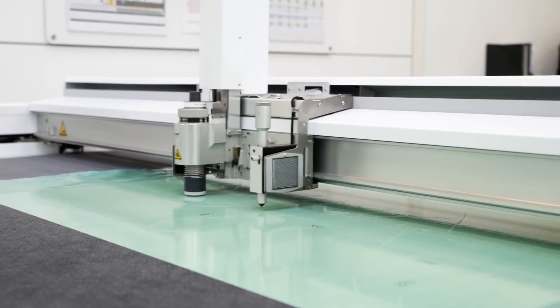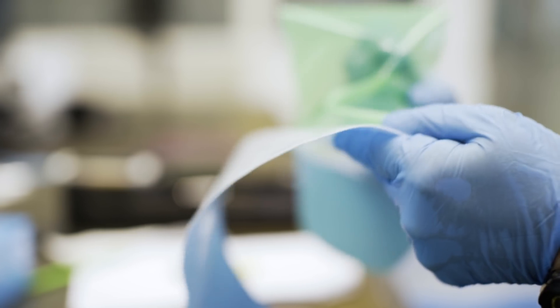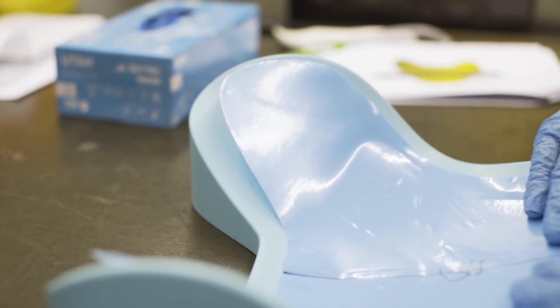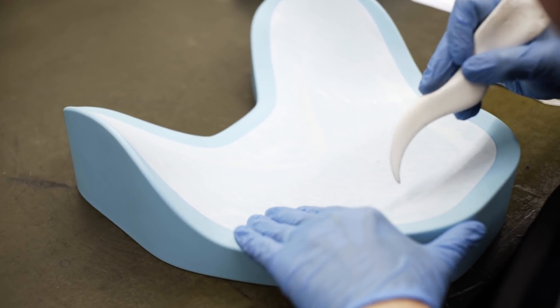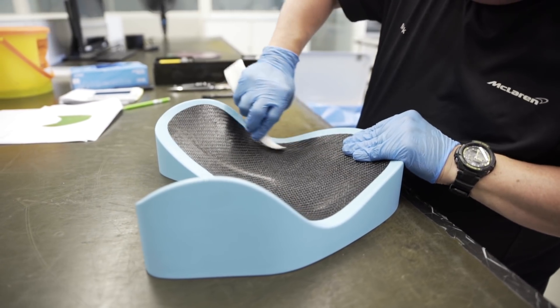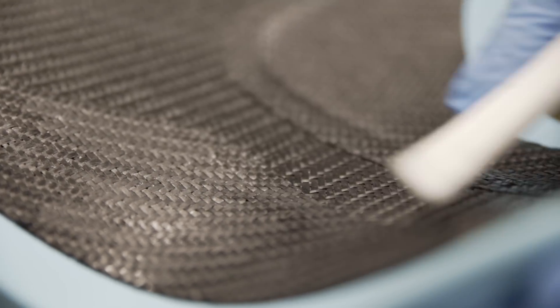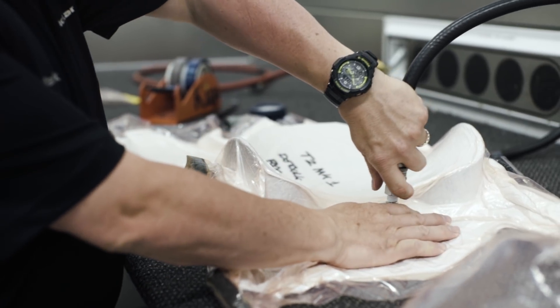The composite shield is manufactured of three different types of fibers held together by a highly toughened resin system. Firstly, stiff carbon fibers providing the flexural rigidity and strength. Secondly, ductile Dyneema fibers, which are used in high performance boat sails and bulletproof vests, as outer layer damage containment and central lightweight core plies. And thirdly, Zylon fibers to provide penetration resistance and energy absorption. Zylon fibers are used by all F1 teams to protect the driver in the event of a side impact. This results in a system that is highly effective in energy absorption and impact attenuation.